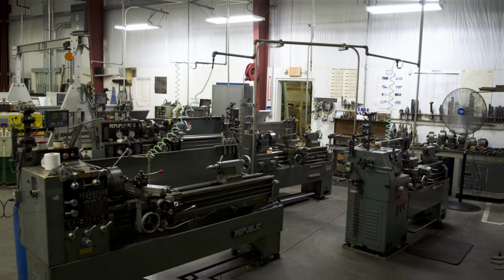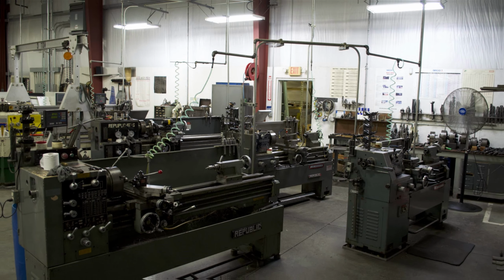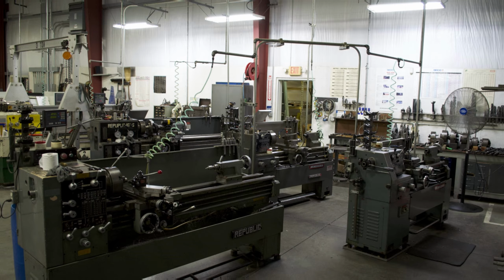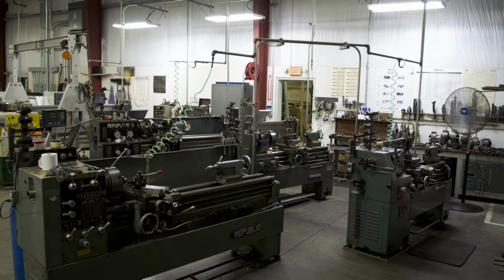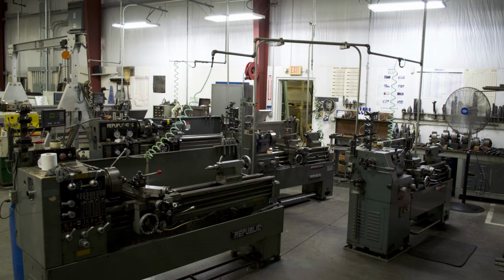Batch 61 heated unevenly, the outer portions reaching proper temperature while the center remained too cool. Half the tools worked beautifully. The other half failed within minutes. Metallurgists could not distinguish good tools from bad until machinists tested them under actual cutting conditions, by which time failed tools had already damaged expensive workpieces.